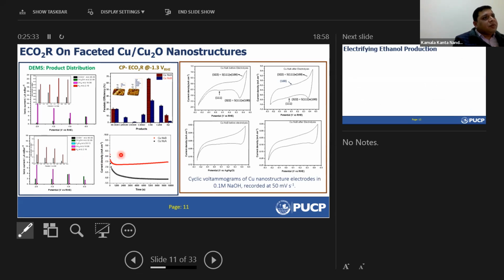Another thing we have investigated is the catalyst surface structure before and after electrolysis. As you can see, the copper 1-1-1 surface changes drastically during the electrolysis, and you obtain a totally different set of facets after electrolysis. But the copper 1-0-0 surface or copper 1-1-0 surface is more or less stable, with a very marginal change after the electrolysis. We'll come to this fact later, the changing of the electrode surface during electrolysis, how it can be a bane, a good thing, or a bad thing in electrocatalysis. We'll come to know about this in my later slides.